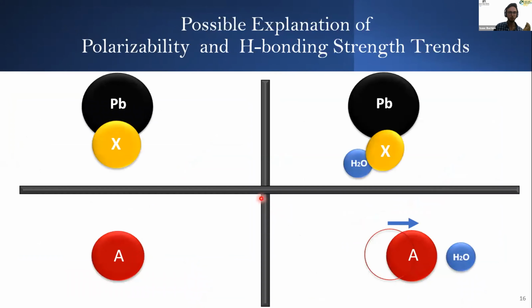Here is a possible explanation as to how polarizability and hydrogen bonding strength could affect the mechanical properties of these materials. When no water is present inside the material, the lead and the X-site anion have the greatest overlap. But when water intercalates into the material and forms hydrogen bonds with the X-site anion, electron density from the lead X-site anion bond is drawn away. The bond becomes weaker and is thus easier to break, which we measure as lower hardness.